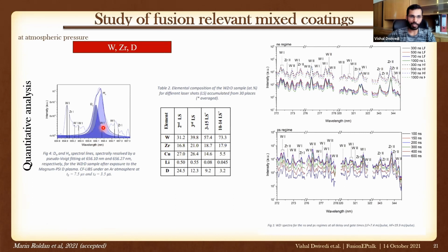We also have tungsten here, the convolution here. So we should again be careful. And here are the elemental compositions. So we can see tungsten, zirconium, copper, and lithium and deuterium. So for different laser shot numbers, second, third to 15 this is accumulation, and 10 to 14.